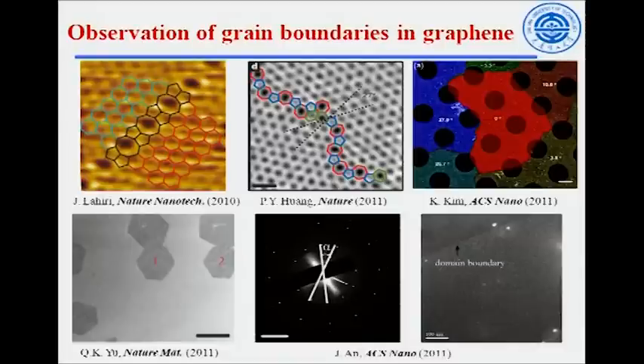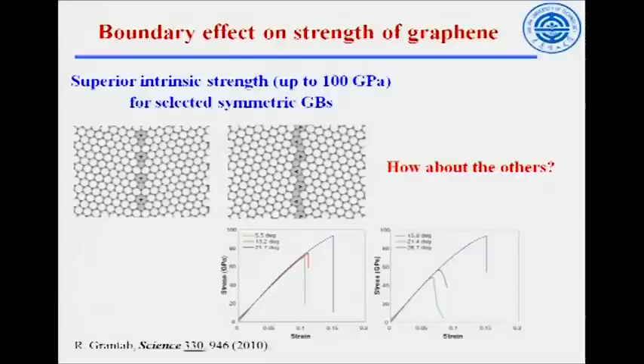However, in real graphene samples, normally you grow polycrystalline graphene. So there are always some grain boundaries between the single crystalline domains. What will be the effect of these grain boundaries on their excellent mechanical properties? Two years ago, a Science paper reported that for some selected symmetric grain boundaries, the intrinsic strength can be very high, almost as high as pristine graphene. So it's up to 100 gigapascal.